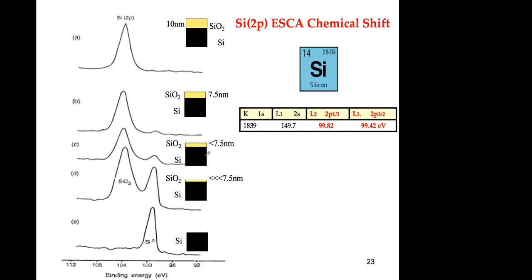And this is an example of how deep you can see things in XPS. For example, if you have a plain or clean silicon surface or silicon wafer, basically you only see one peak for the 2P. But when you start to make an oxide, a very small oxide, much less than 7.5 nanometers, you start to see an additional peak. You see the oxide, and the peak for the silicon is lower because you have this barrier. And as you increase the oxide, this peak starts to decrease more compared to this one. And when you get to 7.5 nanometers, basically it's almost disappeared. And when you have 10 nanometers of thickness of silicon oxide, you don't see the silicon zero. You only see the oxide.